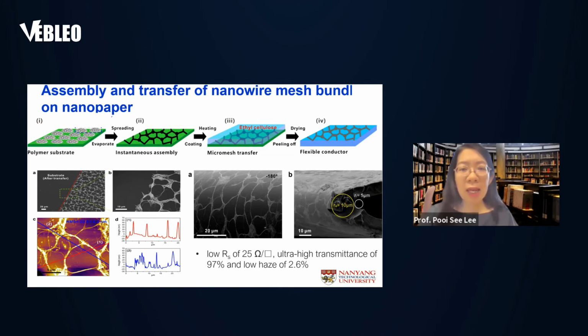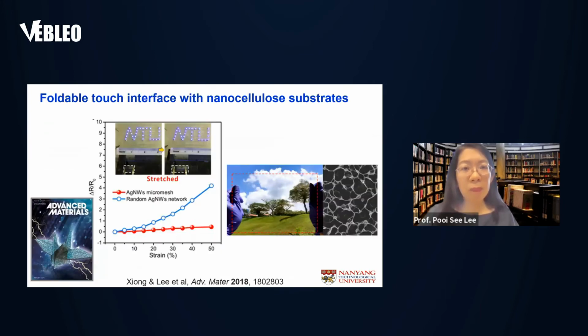Upon drying, it leads to this network structure that has a coiled and bundled network, which leads to a very good transparency, as well as low haze and high transmittance with low resistance. So over here, very thin substrate with a small bending radius can be achieved as well. So this transparent nano paper with a conductive layer can be scalable.